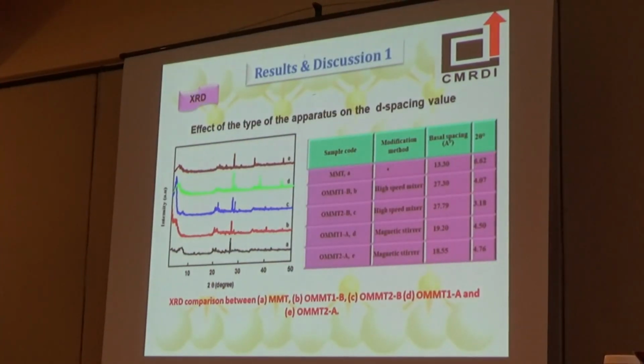Results and discussion. XRD analysis shows that the value of d-spacing for the montmorillonite clay without any modification was found to be 13.3. But with modification using the high-speed mixer, the values increase to reach 27.3 and 27.7. While modification using the magnetic stirrer increases the value to 19.2 and 18.55. From this, we can conclude that modification using the high-speed mixer causes a greater d-spacing value.